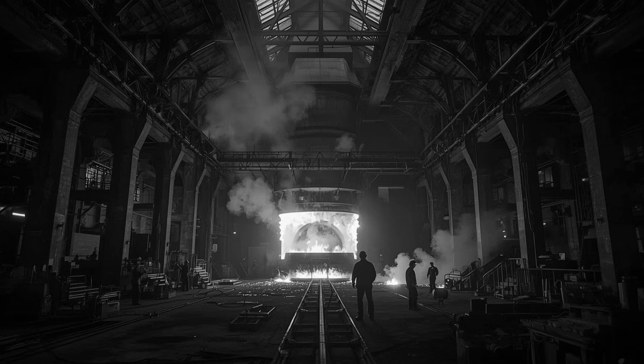The breach in the chimney lining was the primary fault. It had likely existed for months, possibly since the last major refit. The inner bricks had expanded and contracted through thermal cycling, and the mortar had failed. The gap had started small, then widened over time as cold air infiltration eroded the edges. By the night of the incident, the opening was large enough to admit significant airflow, enough to cool the exhaust gases, enough to weaken the draft, but not enough to extinguish the furnace under normal conditions.